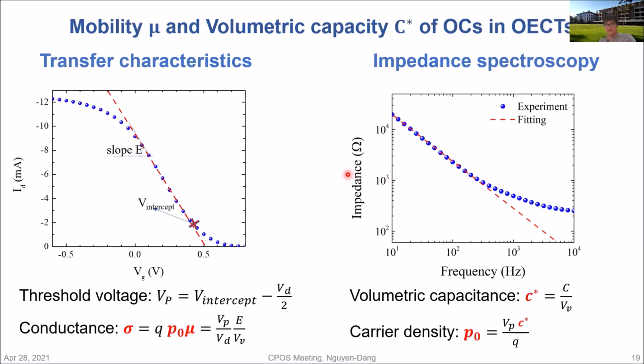In terms of performance of the PEDOT:PSS, in this slide I show how I characterize it using the transfer characteristics. We can extract certain values, basically the threshold voltage and the conductance. And using impedance spectroscopy, we extract the capacitance of the film. From these two values, we can extract the conductivity of the film. We can extract the hole mobility, the charge carrier density, and the volumetric capacitance. Those are the four figures of merit that I use to evaluate my devices.